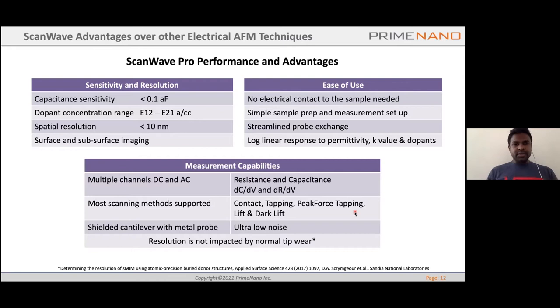The other factor is the probe itself is a metal probe, and that actually gives us much more lifetime for the probe, and you're not impacted by the normal tip wear when it comes to the spatial resolution for the electrical information.